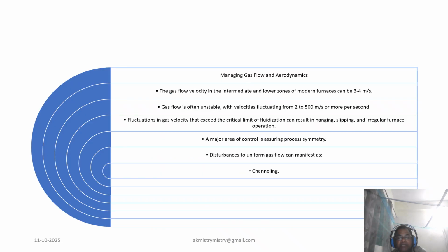The uniformity of the gas is critical. The gas velocity in the lower zone can be high, around 3 to 4 meters per second. Fluctuation in this gas flow or channeling must be managed, as flow exceeding the critical limit can lead to irregular descent, hanging, slipping, uneven reduction, and fluctuation in the chemistry. Our goal is to manipulate the gas distribution to improve the smooth operation index.